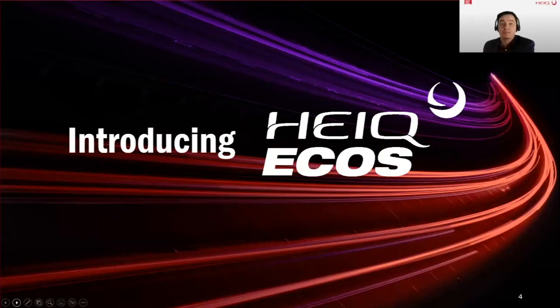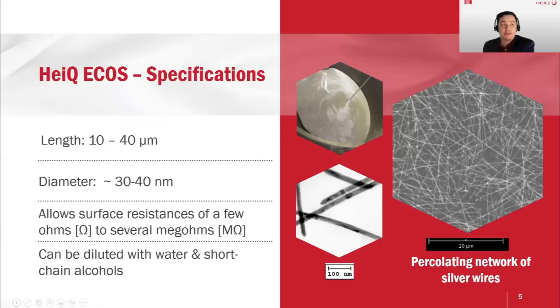HeiQ ECOS is based on silver wires. We manufacture these silver wires via a patented process with very defined size dimensions. So around 30 to 40 nanometers in diameter and 10 to 40 micrometers in length. And we do not make these silver wires in form of a powder, always in form of a dispersion or coating formulation.